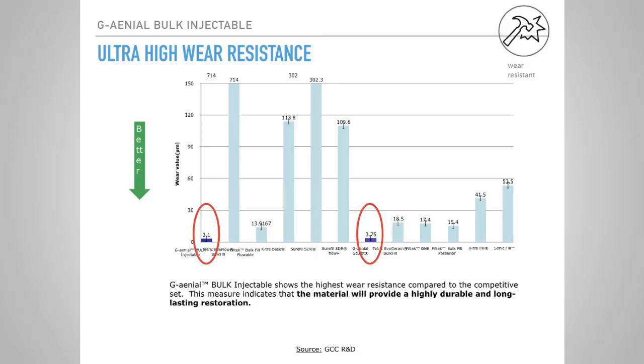So when we get into the ultra-high wear resistance, we can see without a doubt that the material will provide a highly durable and long-lasting restoration because of the way that this material tested out. The wear resistance is phenomenal. And so that's the beauty of this material. And that's the game changer that GC has presented here, is that we have a material that's flowable, can get into the cavosurface area, is bulk fill or 2 millimeter fill, and can resist wear.